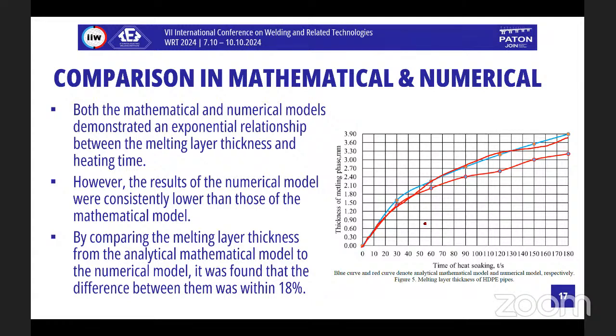From this picture, we can see the results from the numerical model were consistently lower than those of the mathematical model. That's because in the numerical model, I considered the heat convection between the ambient environment and the surface of the high-density PE pipes, but in my mathematical model, there is no such consideration. By comparing the melting layer thickness from the analytical mathematical model to the numerical model, it was found that the difference between them was within 18%.